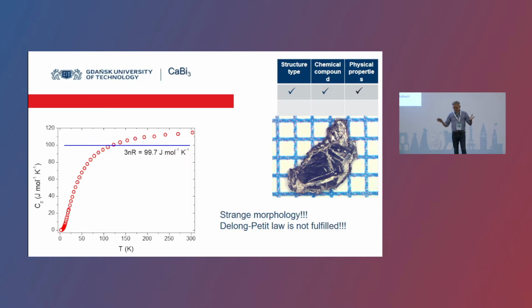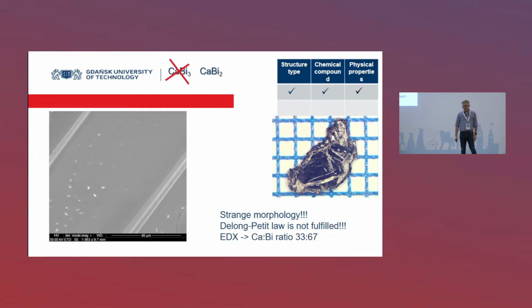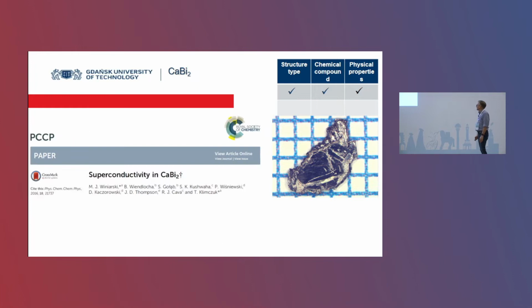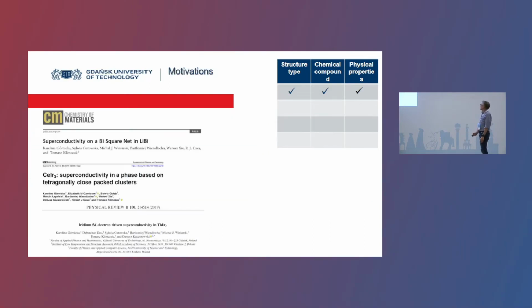Of course, it's strange because calcium bismuth 3 is supposed to form in a cubic phase, so it's not a cube. And besides, another point which is strange is the fact that we are way above the Dulong-Petit law. So we checked the EDS, and it appeared it's not calcium bismuth 3, it's calcium bismuth 2. But still, it's a superconductor with Tc 2.2. It's a very interesting superconductor because the bismuth forms a square lattice, and because it's a 2-dimensional superconductor. The paper was published, I think, like 5 years ago or so.